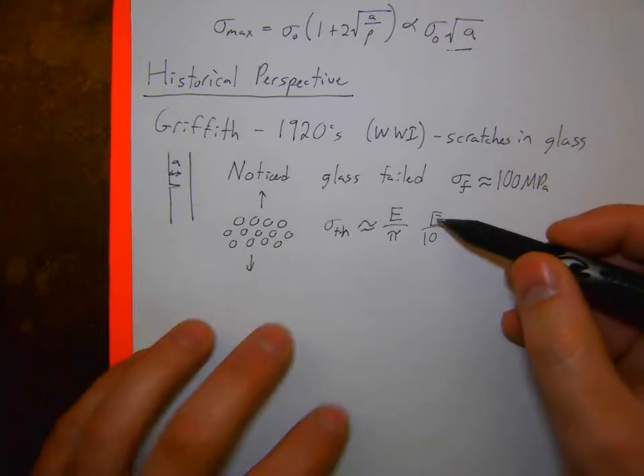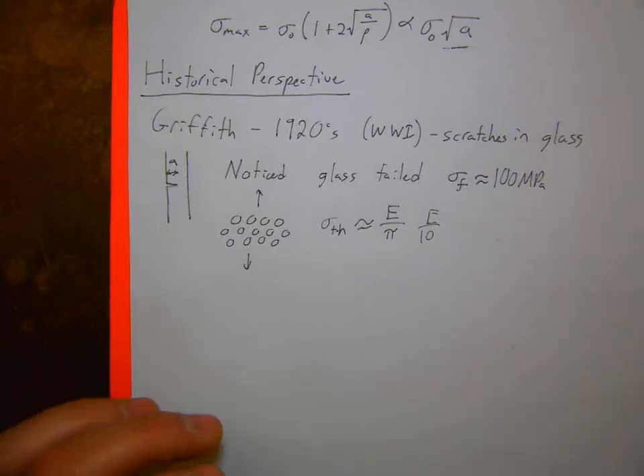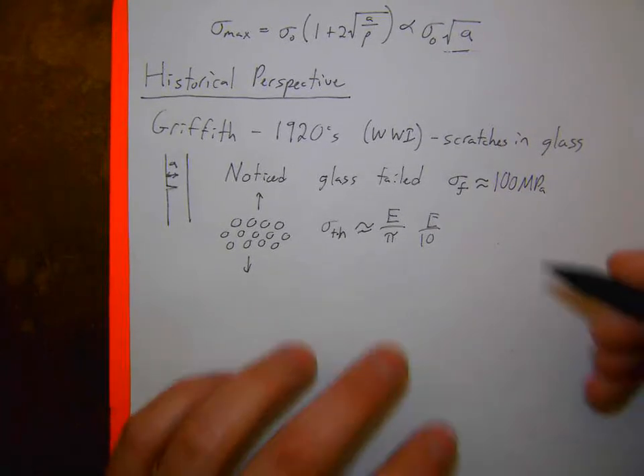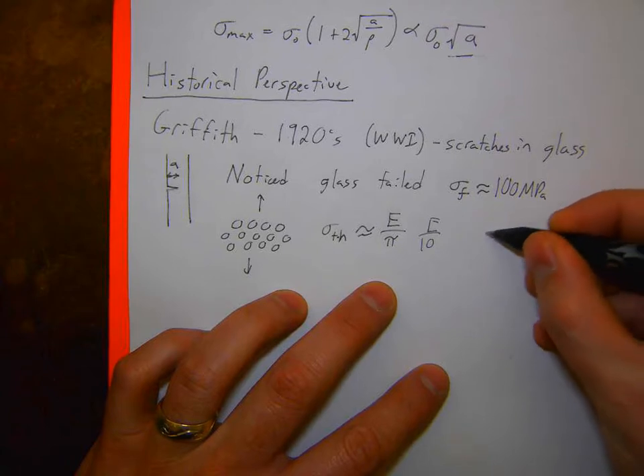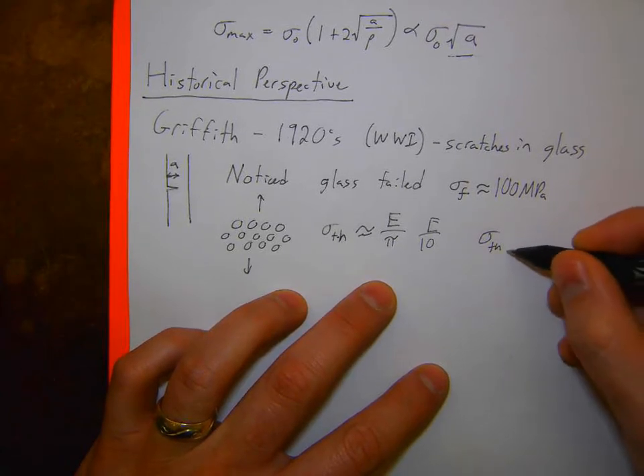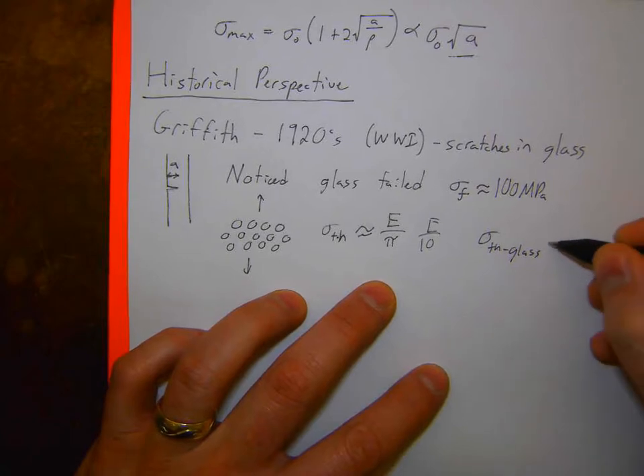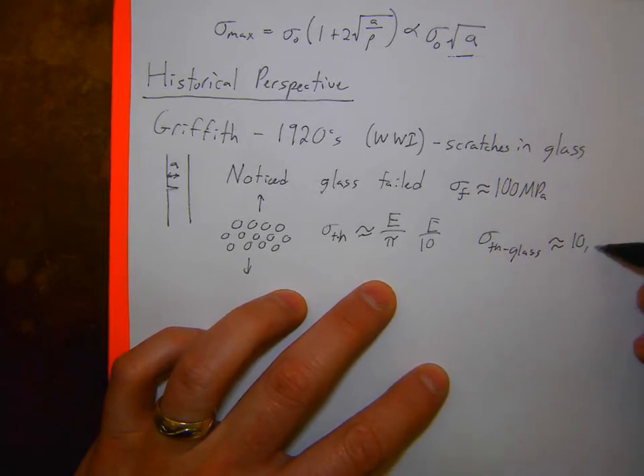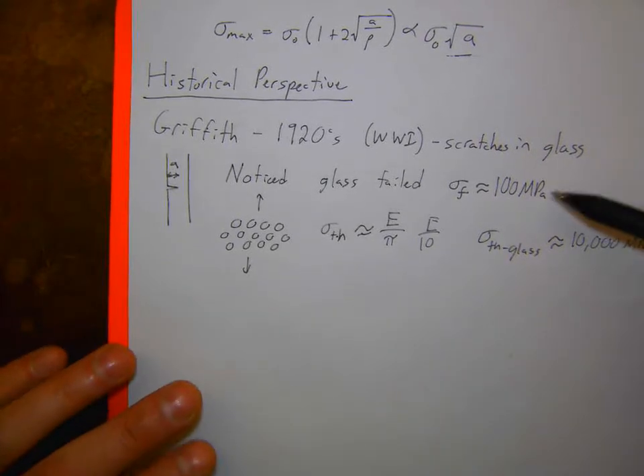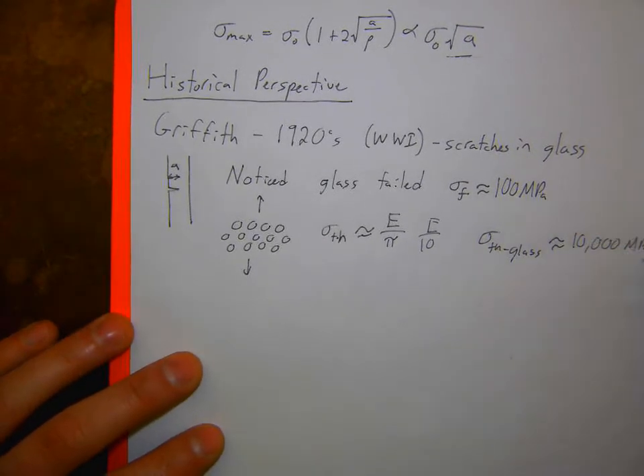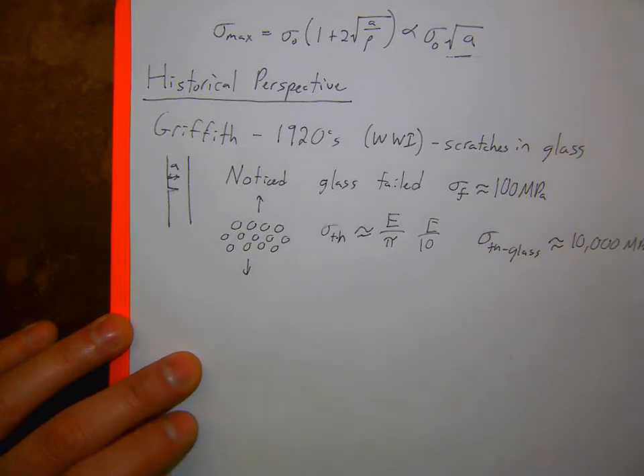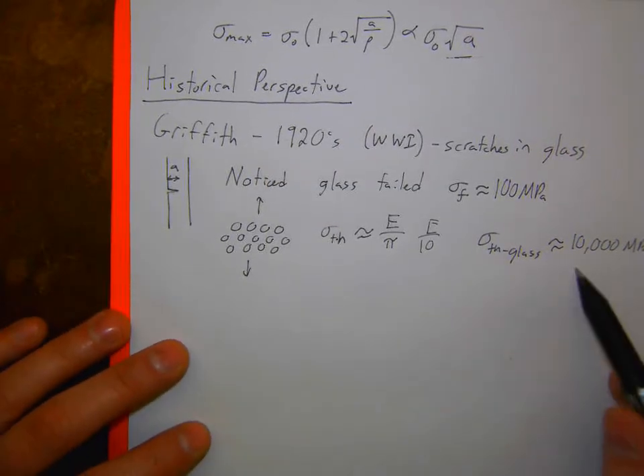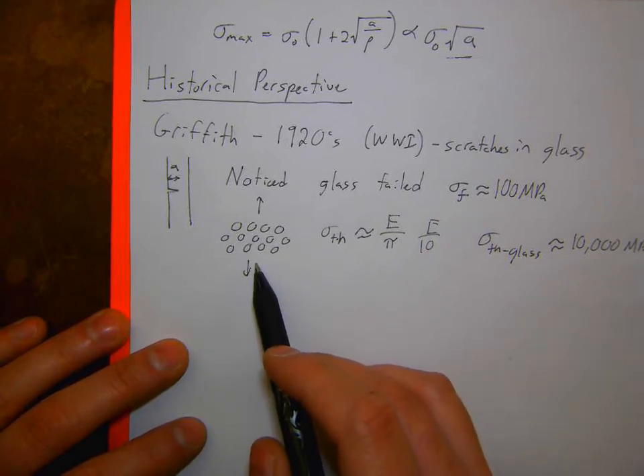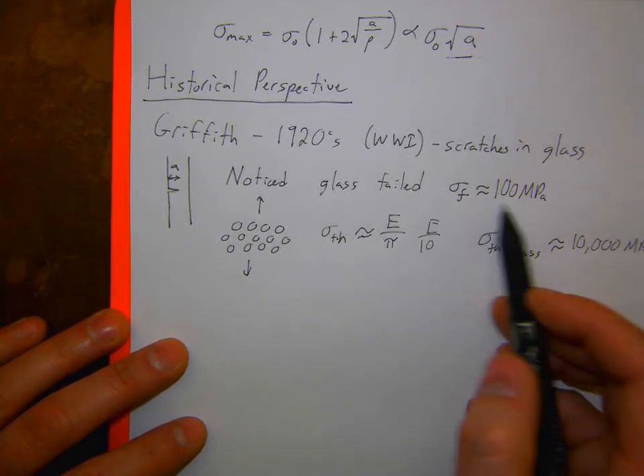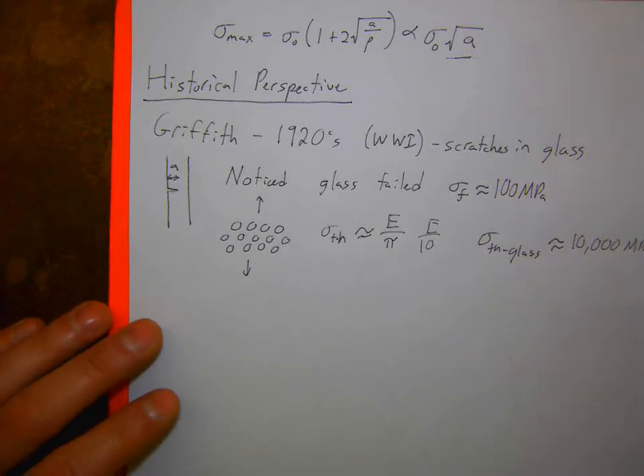So the Young's modulus of glass is like 50 gigapascals. So we would expect something theoretically for glass, sigma theoretical for glass, is on the order of actually 10,000 megapascals. And so, prior to this study, Griffith noticed that there was this large discrepancy between these two values. So he's like, well, theoretically, this glass should be a lot stronger than we're seeing. And so he wanted to try to figure out why that was the case.